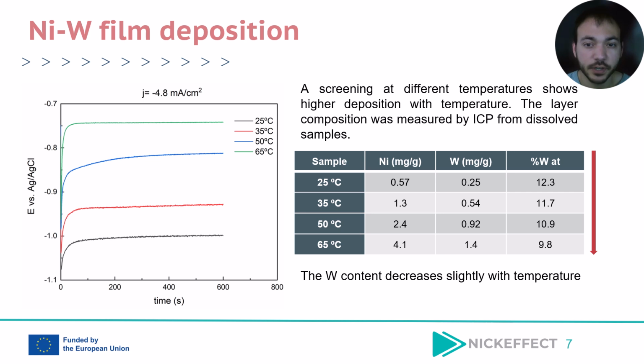First, we did a screening depositing samples at several temperatures and current densities. As you can see in the table, the amount of metal deposited increases with temperature. On the other hand, the tungsten content of the sample slightly decreases. Having said that, all samples have a similar tungsten content ranging from 10 to 12 atomic % of tungsten.